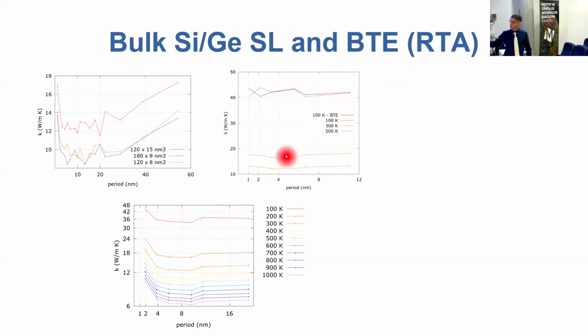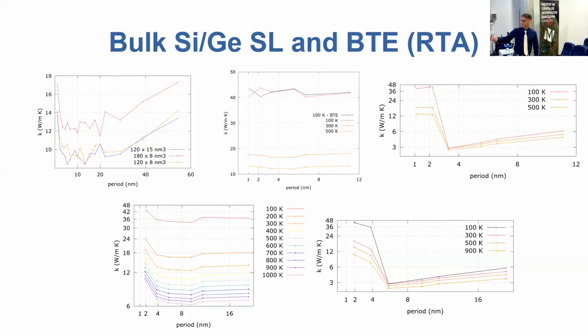We also repeated this simulation with not rough, but chemically mixed interfaces for the two crystal directions, 111 and 100, and you can appreciate that the introduction of a slight chemical mixing really sharpens the decay of the thermal conductivity when we move from the coherent to the diffusive regime, and also enhances the linear dependency of the thermal conductivity with respect to the superlattice period when we move to longer and longer periods. So after all of this, this concludes our study of thermal transport across the single interface and multiple interface cases, and we can spend some time talking about Raman spectroscopy.